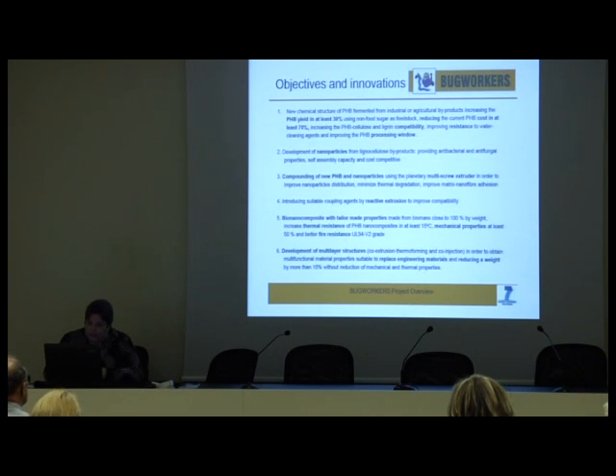The nanoparticles will also be produced in the frame of the project. The compounding of the PHB and the nanoparticles will be done using a planetary multi-screw extruder. It's equipment that allows obtaining a very good dispersion of the particles, could be nano or not, but with a low shear rate. In this case, we obtain a good dispersion with lower degradation when we use natural fibers, in this case, biopolymers.